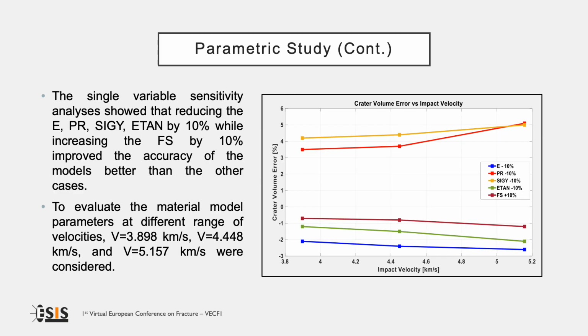The previous results were obtained for an intermediate impact velocity. We can consider the set of parameters with the least error, so the one with the elastic modulus, Poisson ratio, yield strength, and tangent modulus decreased by 10%, or with the failure strain increased by 10%, and evaluate the error by changing the impact velocity. As shown in the diagram on the right, the error increases if the impact velocity increases.